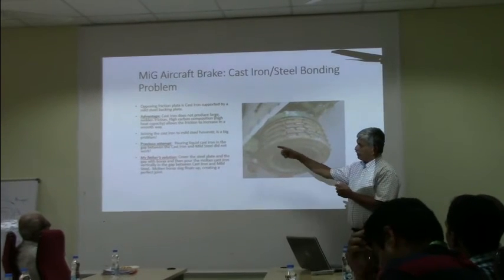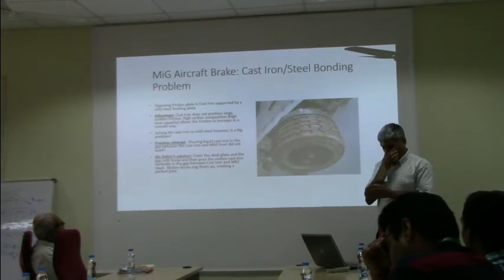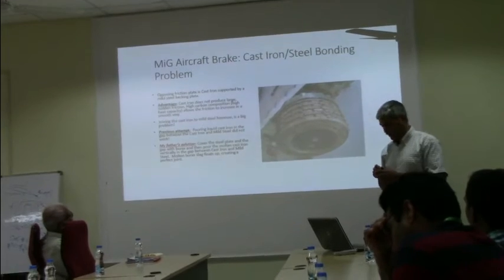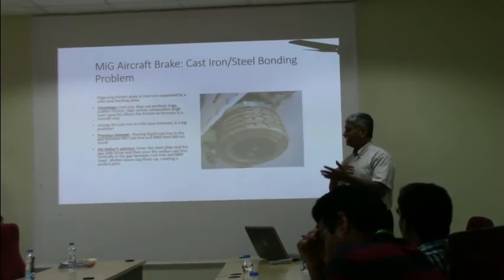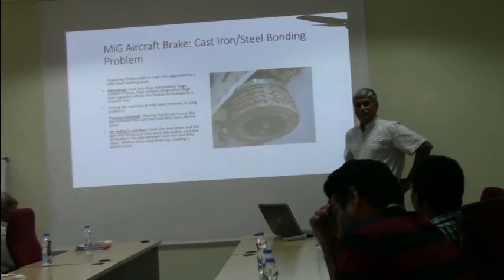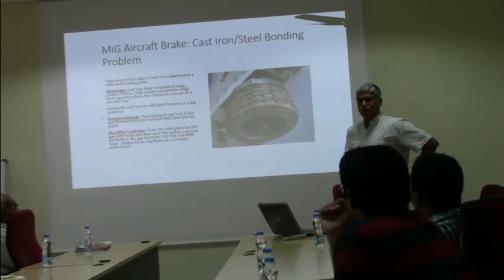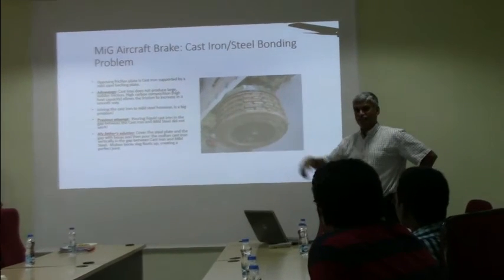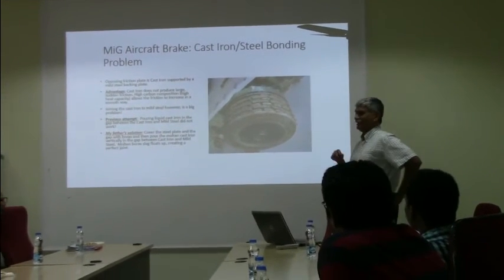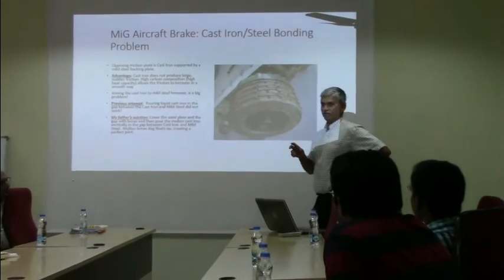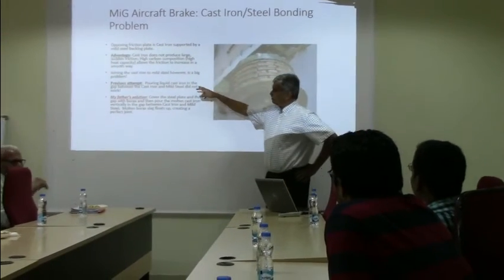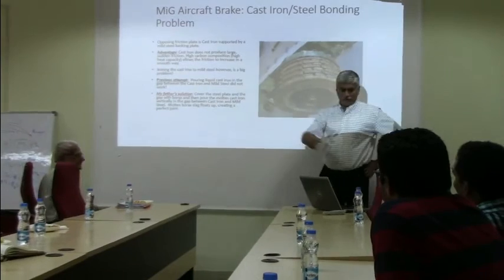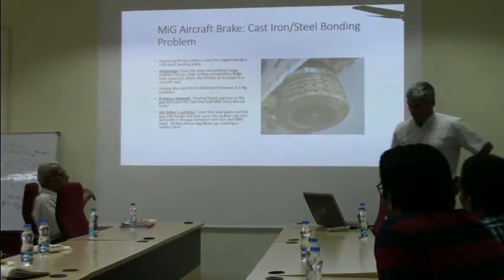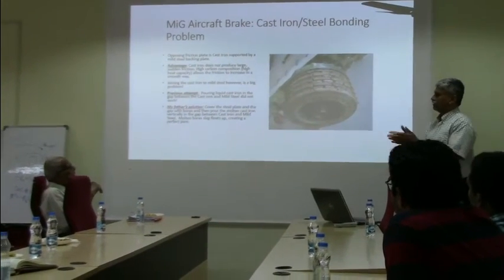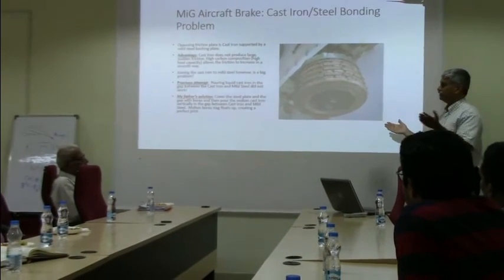And so with previous attempts, one of the problems which happened, and I'll mention this mildly, is that because of his interactions with the director, the director used to usually pick another scientist to try the project out. And when they couldn't succeed, they would come to my father, right? So this previous scientist tried to pour liquid cast iron in the gap between the cast iron and the mild steel, and it did not attach, right?